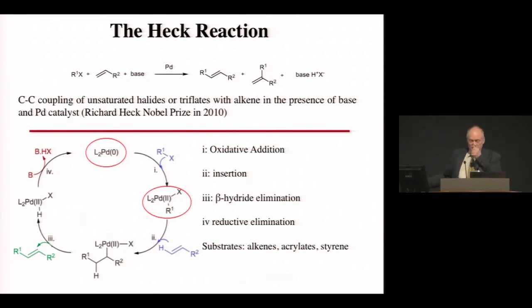Okay, so what we can do is we can make a sensor. If we had a bunch of this around and none of that, we can make a sensor for the halide, or we can make a sensor for the alkene. So in this case, if we have the palladium all in this state, every time we add some of this alkene, it's going to make some palladium-0. It's going to reduce our nanotubes, change the conductance, and then it'll gradually come back over here and the conductance will go up again. So we'll bring the conductance down by making palladium-0, bring it back up by making palladium-2.